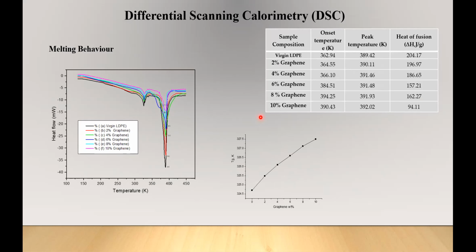Now we are going to the melting behavior. This peak shows the melting behavior. And this thermogram is used to determine a number of parameters here, that is onset of temperature, peak temperature, and heat of fusion. So melting temperature of crystalline polymers normally depends on the size and perfection of their crystal units. Here the melting temperature of LDPE depends on the filler particles of the composite. The virgin LDPE shows the melting temperature at 389.42. You can see it here.